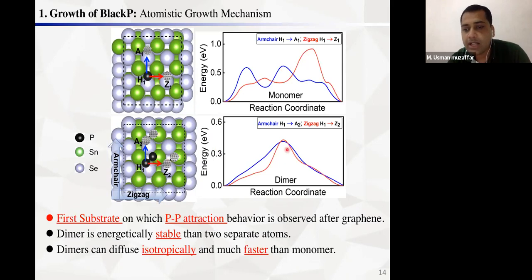Then we calculated the diffusion barrier, and we find that the diffusion barrier of the dimer is much lower than that of the monomers. You can see here the diffusion barrier maximum is 1 and minimum is 0.6 eV, but in this case, the dimer only needs to cross a barrier of just 0.4 eV. So it means that the dimer can move faster than the monomer. Moreover, if we look closely, along the zigzag and along the armchair direction, they move isotropically.